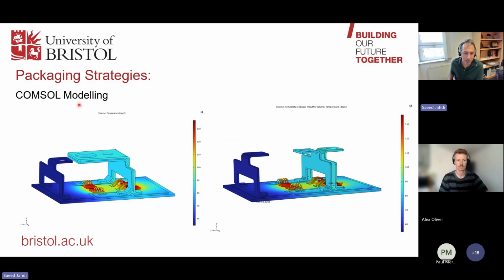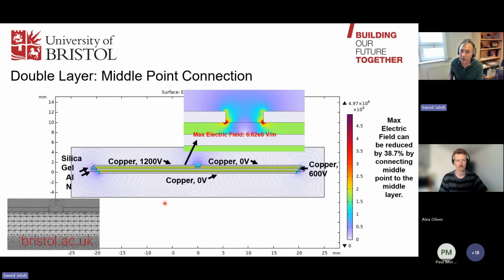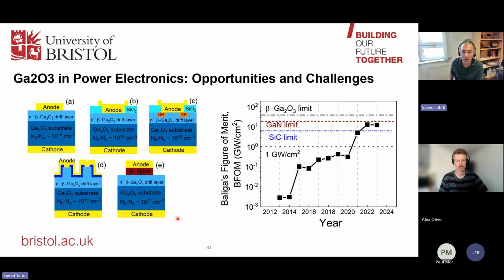Well, by we, I mean our PhD students and postdocs, and we can see that the temperature rise in terms of the devices and the maximum temperature that the modules have to endure is acceptable. The partial discharge and the max electric field is within the limits that you would expect, and this double layer ceramic can also actually alleviate that as well.